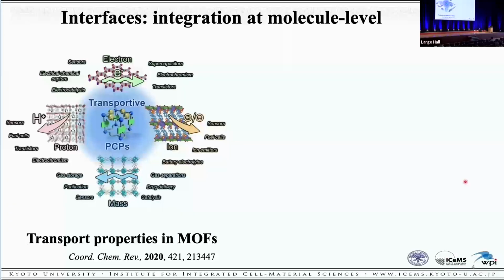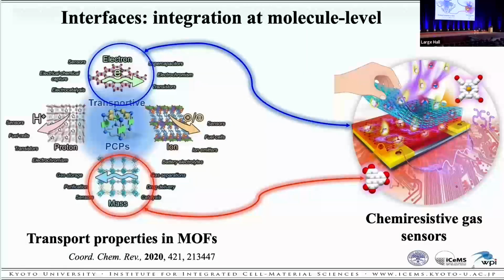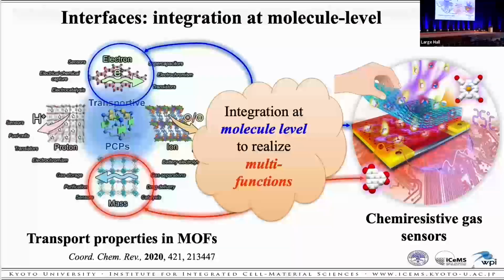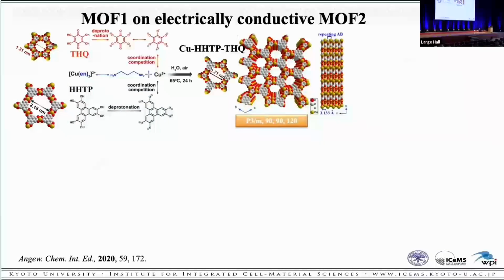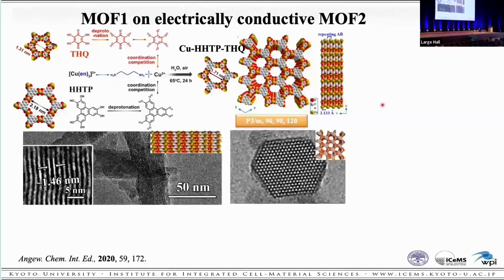Here, as a result of two case studies on the application of MOF hybrids to sensors. A new 2D conjugated electrically conductive MOF containing copper units with mixed trigonal ligands was developed. This is the Cu-HHTP and THQ system. The gas sensors based on these materials, nanowire thick film, were fabricated on insulating substrate with pre-deposited gold interdigital electrodes by the drop coating method, followed by activation under flowing dry air at room temperature. So the layer structure grows here, like here.